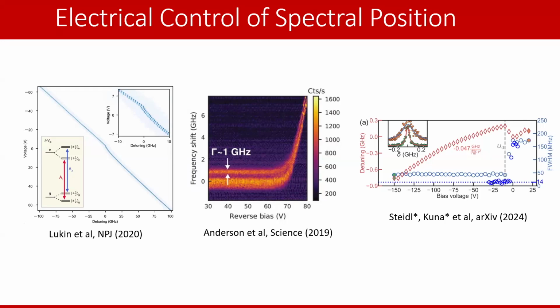How do you use the depletion region to your advantage in this case? The reason that the defects move in time is because of moving charges within the silicon carbide lattice, electrons and holes. If you provide a depletion region, you quite literally sweep out all of the electrons and holes in that area. Fortunately, this doesn't destroy the defect, because you can imagine that if you really got rid of all the electrons and holes, then you would get rid of the defect too. But the defect state is strong enough that this doesn't happen. So you just remove all of these moving charges, and by removing them, you no longer have stray electric fields close by that tune your center frequency.